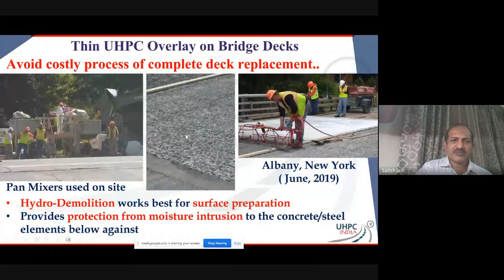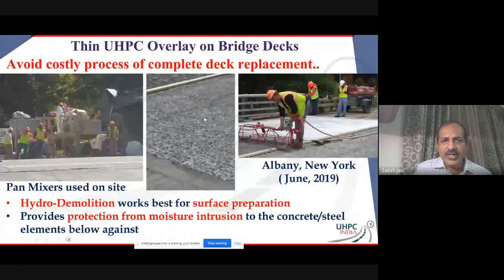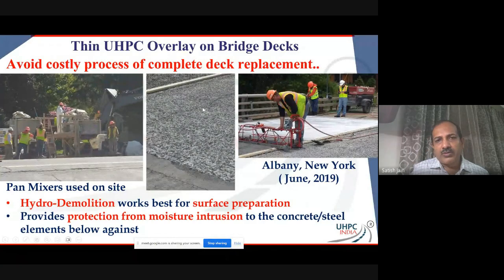See the roughening process. The underlying concrete was roughened so nicely. You could use hydrodemolition. You can use a combination of milling and hydrodemolition. But you need a good roughened surface for good bonding purpose, right? And then this was a simple project, so a very simple truss screed vibrator was used over here. And immediately after putting that, they are spraying a curing compound after screeding it. Curing compound is put so that evaporation can be arrested.